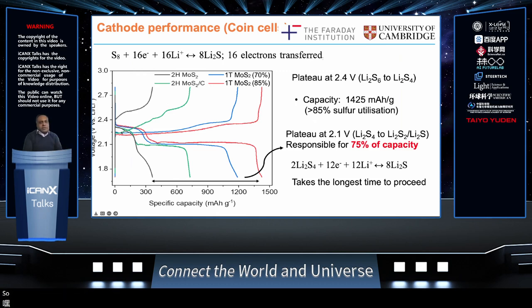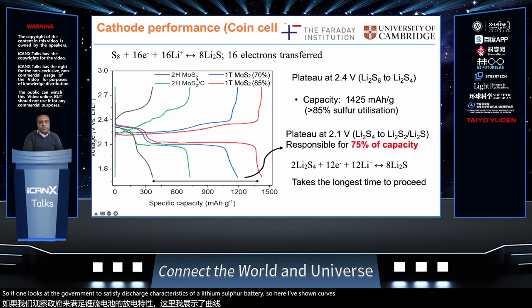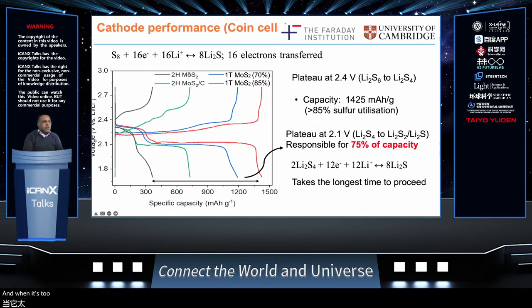So if one looks at the galvanostatic charge discharge characteristics of a lithium sulfur battery, here I've shown curves for different MoS2 electrodes. So this is the semiconducting MoS2. To increase the conductivity of the MoS2, we've added carbon and made some electrodes from that and different concentration of 1T phase MoS2. And we see that the pure 2H MoS2, the semiconducting phase, is too insulating to give any measurable capacity.